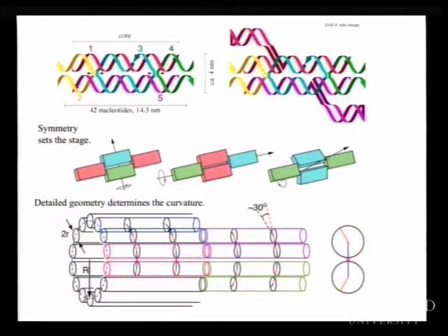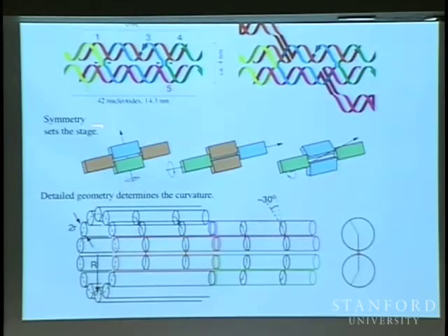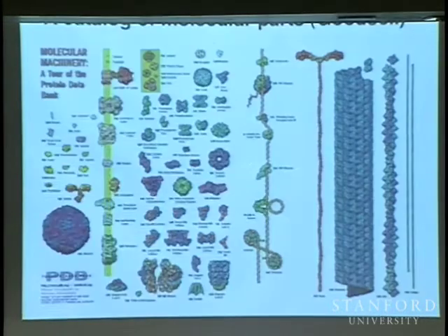These little bricks had four corners that had little single-stranded pieces of DNA hanging off. So there's the double-stranded part, and then there are these single-stranded parts, which had free open A's, C's, G's, and T's that could specify the interaction of these bricks with each other. So these bricks could come together. These are bricks that are all supposed to be the same, but the different colors show the symmetries of how they come together. The point is, these particular bricks come together at an angle. And so these bricks could form a tube that's not unlike this girder that you see in cells.